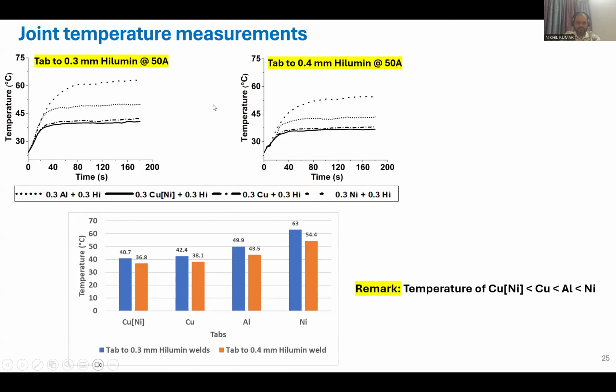And this is joint temperature. As I mentioned, I am capturing the temperature at the same time while passing the current. So the resistance is measured by two probes, by measuring the voltage drop, and the temperature is captured by the IR camera. So I am focusing the IR camera around the weld, just on top of the weld, and capturing the temperature rise, because according to Joule's law of heating, as you are passing the current, I squared R t. So as you increase time, you increase the heat generation as well, and that is increasing the temperature on the sheet, which is captured using the IR camera.